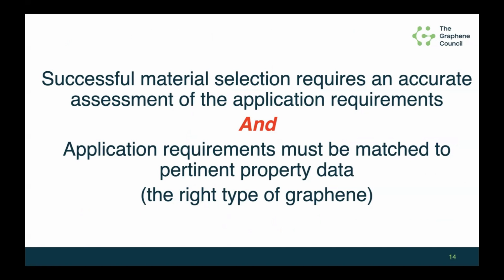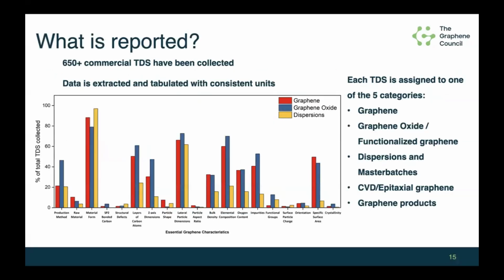So for successful material selection, we require an accurate assessment of the application requirements, and these application requirements must then be matched to the pertinent property data so that you are able to select the right type of graphene. So as the Graphene Council, we have analyzed more than 650 commercially available technical data sheets from different producers of graphene. This data is then extracted and tabulated with consistent units, because most of the different TDS report data in different units. And then this data has been segregated into 19 essential graphene characteristics.